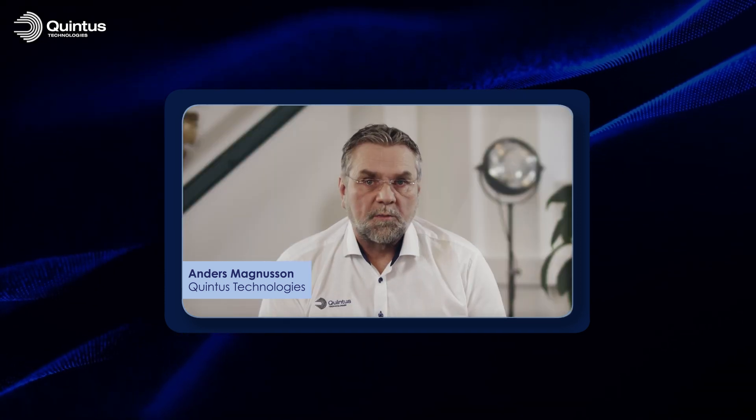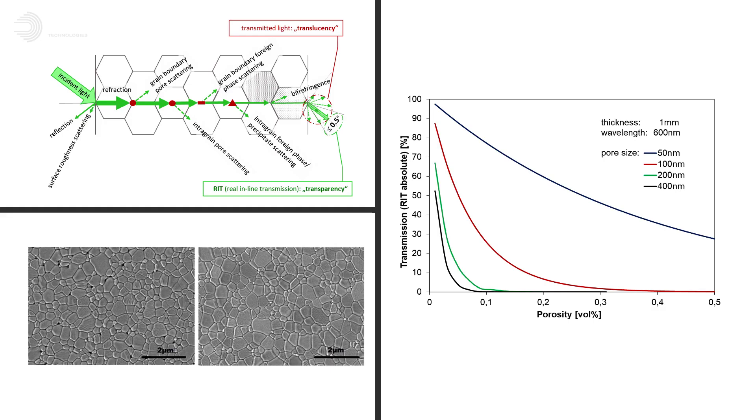For the audience, could you please tell us the difference between glasses, transparent ceramics, polycrystalline transparent ceramics, and single crystals? A glass is something like a frozen liquid — it has an amorphous state of material, whereas a single crystal is one grown crystal that grows from the melted material. Polycrystals are several billions of very tiny crystallites which are baked together into one composite material. For a transparent polycrystal, it is most important that it is sintered without any porosity — we need less than 0.01% porosity to make the material transparent, and this is a really challenging task.